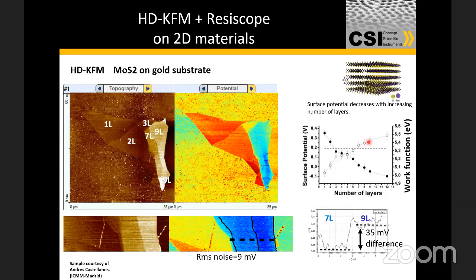So what the measurement is essentially demonstrating to us is that the surface potential of MoS2 decreases as the number of layers goes up, and I guess that's intuitive, right? I would like to add one more thing. If you see this bottom right image, you see this dotted black line. That is basically called section analysis.